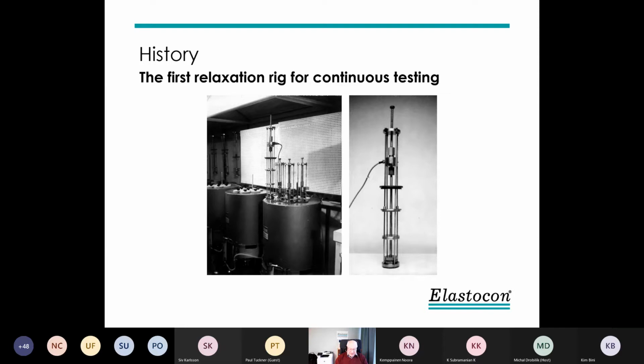So I was participating in that standard group, and I worked at that time at the National Testing Laboratory in Sweden, or Testing Institute. And we found that the best thing is to measure continuously and not measure discontinuous, because then you get much more errors. So this was the first design of a continuous test rig. And of course, we also needed a heat source, and we used a cell oven for that purpose. But the cell oven was quite small cells and deep cells, and became quite long.